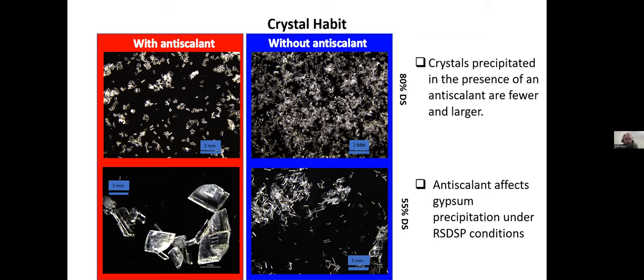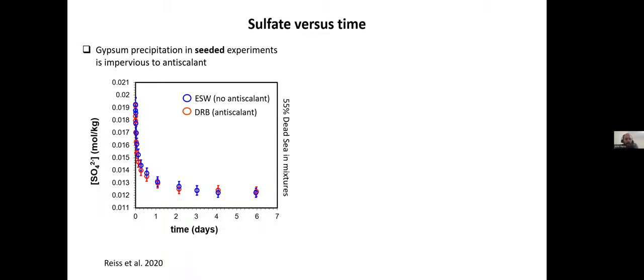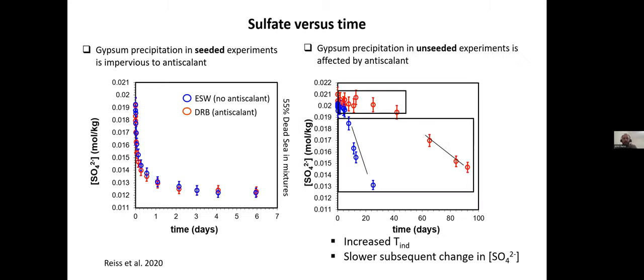However, I was interested in how this works mechanistically. So if we look at the seeded experiments, where I have only crystal growth, it appears that the rate of crystal growth is impervious to the presence of scale inhibitors. However, if I look at the same chemical compositions where I have nucleation and growth, we see in the red dots that I have a much extended induction time, the time until I could observe a change in the system. And after the induction time, the change in sulfate with time with the scale inhibitor is slower. So the presence of the inhibitors impacts the nucleation and the overall rate of precipitation.